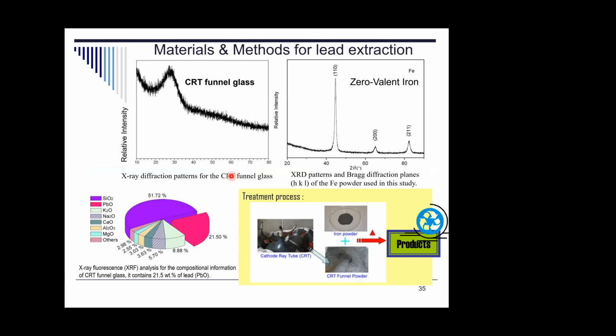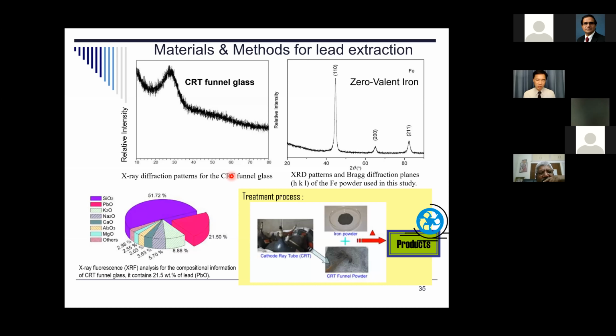So what we were thinking is that what we really want is to have the glass network react with something in a solid state reaction, if not also melt it a little bit. But at the same time, we want to get the lead 2+ ions back to lead metal. If that's the case, then we can just crush the glass and use mechanical processing, using the difference in physical property, density, to separate the lead metal. So the key thing is to reduce the lead into metallic lead.